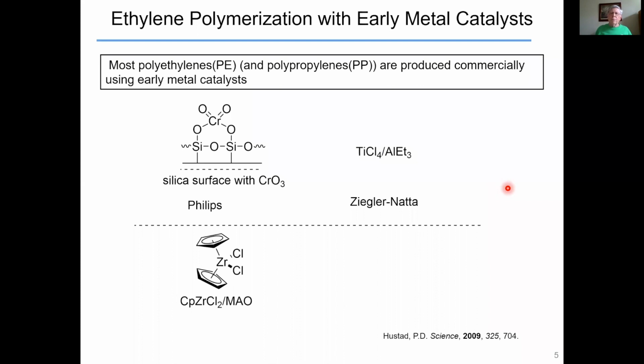So most polyethylene, and polypropylene for that matter, is produced commercially using early metal systems. You can use Phillips catalysts, which are basically chromium-based catalysts, chromium supported on silica. You can use Ziegler-type catalysts involving titanium halides activated with aluminum alkyls, and a lot of polyethylene is now made using these so-called metallocene systems.